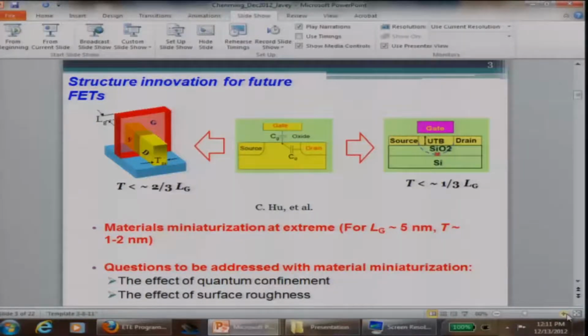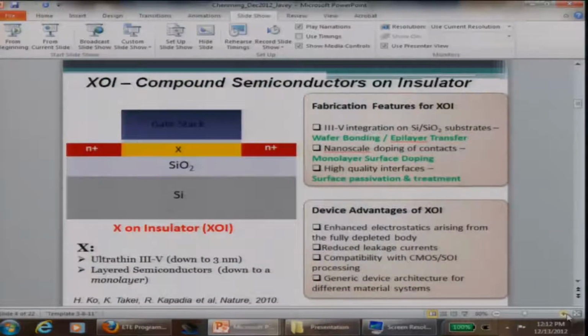So if you think about a device with a thickness of 1 or 2 nanometer, now a lot of interesting effects come into play: quantum confinement, surface roughness scattering that we didn't have to deal with before. So what we're trying to do at Berkeley is motivated by this structure, the ultra-thin body structure. We're trying to use this structure, but replace the top silicon layer with X, with a very thin layer of X. And X here could be either an ultra-thin layer of III-V, and we have done it down to 3 nanometer, or it could be a layered semiconductor, and it could be down to a single monolayer of a layered semiconductor, which I will show you.